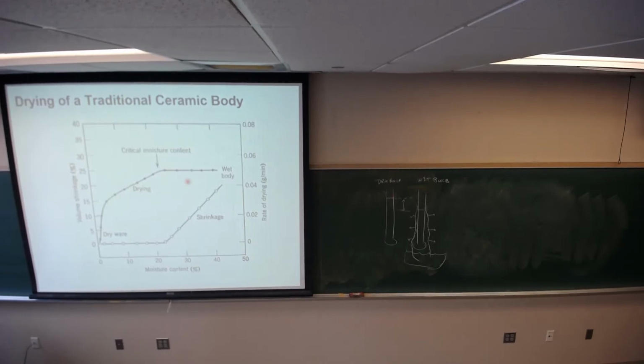And so if you have a wet surface, the temperature of that surface is cooler. And that difference in temperature between dry bulb and wet bulb is dictated by the humidity in the air. So you can argue it's also dictated by temperature, but humidity. So if you have low humidity, then your evaporation rate of water from that surface is fast. If you have high humidity, then the evaporation of water from that surface is slow.